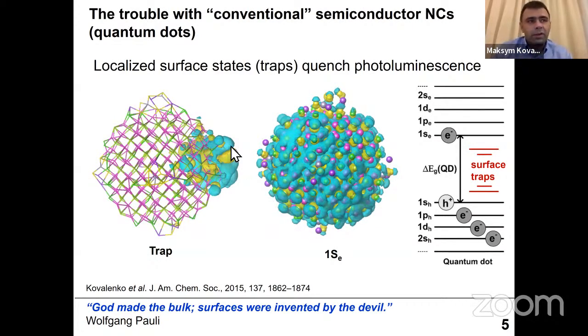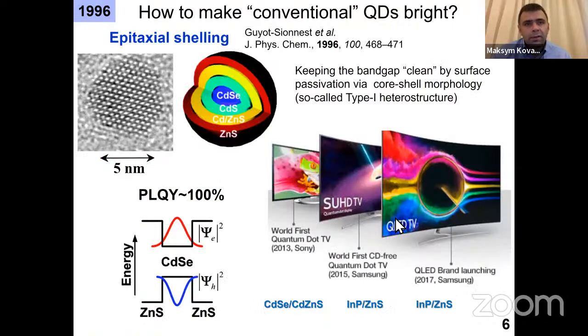And the reason for that was the surface which quantum dots have. They have a very high surface to volume ratio, and the surface is basically made of dangling bonds. Basically, you cut the lattice, you create dangling bonds, so orbitals which are not binding and not anti-binding. And so they are mid-gap states, right, which exist localized on the surface. And even in a very small quantity, they are capable of quenching the electron or hole, thereby basically preventing efficient luminescence. So what people have done since very early on, they focused on how to resolve this